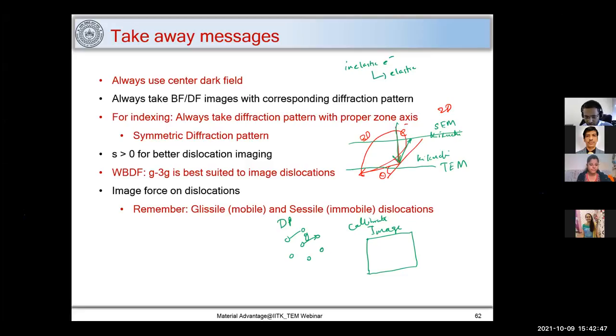So you have this G vector, and when you identify how this pattern is rotated with respect to the image, you just put it parallel on this image. So let's say there is no rotation in this case. What I do is that I'll just put this mark as a G vector here. That is how you put the G vector on your image.